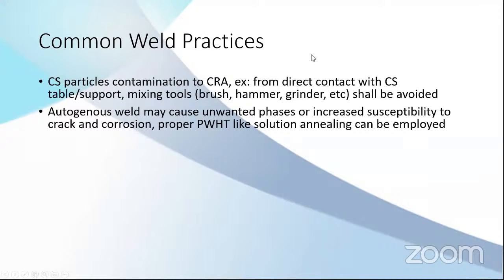And if possible, weld with filler, because if it's autogenous, it may cause problems because of unwanted phase precipitation or increased susceptibility to cracking and corrosion. Or if it's a must, if an autogenous weld cannot be avoided, proper post-welding treatment is to be completed.